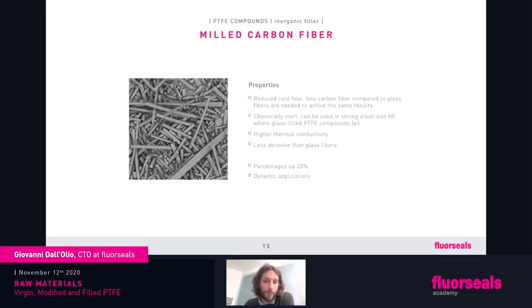When it comes to glass fiber weak points, we will suggest a carbon fiber additive. Basically, carbon fiber has almost the same properties as glass fibers, but you can achieve the same performance using less filler inside. It's also more expensive, so it's balancing this, but the carbon fiber is not attackable by anything, so it will keep the chemical resistance of PTFE, and also it is not an abrasive filler. So when you have a dynamic application and the mating surface is soft metal, for example, glass is not suggested, but carbon fiber will be the right choice for you.